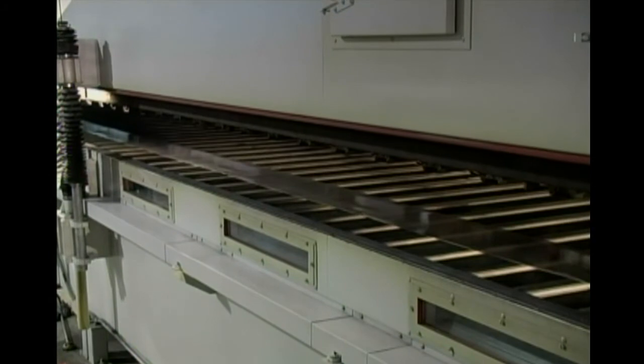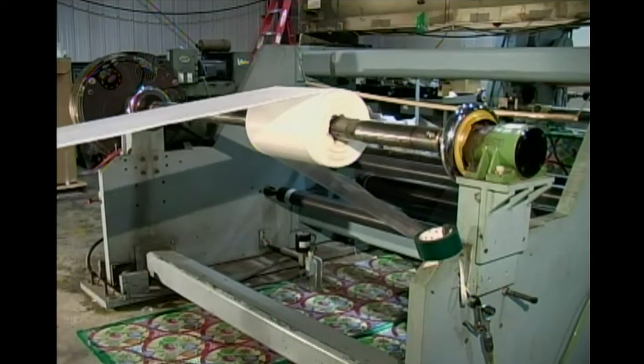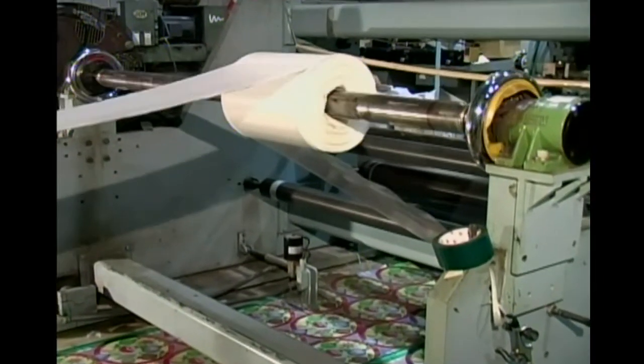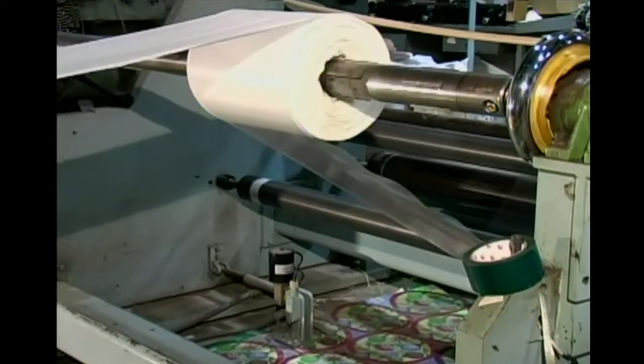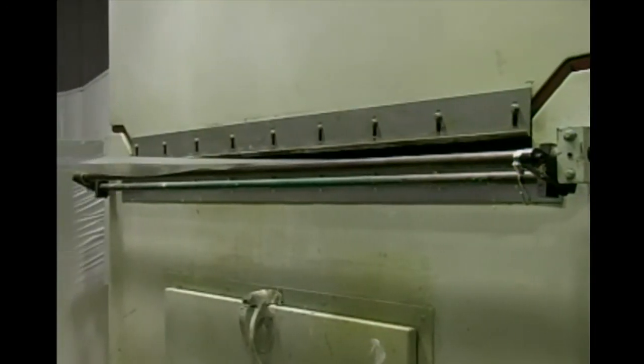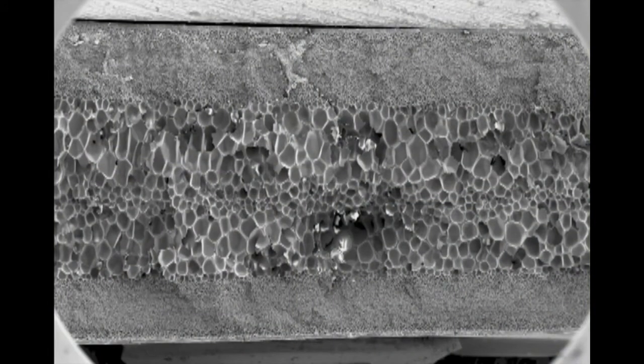and the flotation oven closes. The saturated polymer is fed through the flotation oven, while the interleaf material is recovered for reuse. Note that the interleaf material is white, while the saturated polymer is still clear. The oven heats the polymer up to the point where it becomes plastic, and the carbon dioxide forms billions of tiny bubbles within the thickness of the polymer and a solid integral skin on the surface.